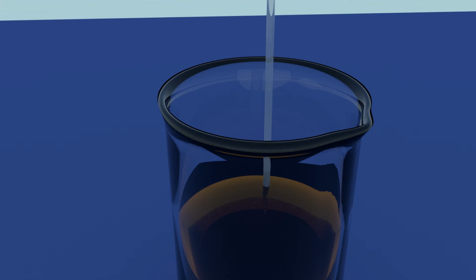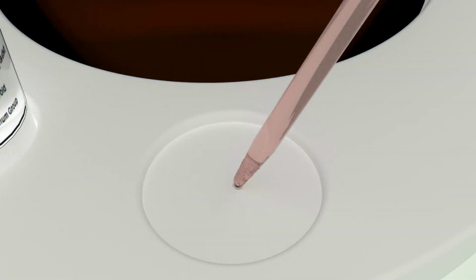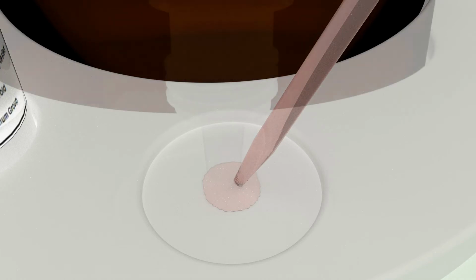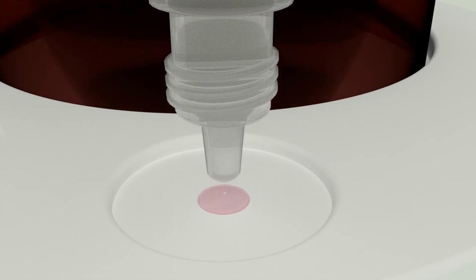To perform this test, you will need to take a sample of your solution. Traditionally, a pipette is used for this purpose. However, since you only need 1 or 2 drops of solution, you can use an eyedropper or even a glass or plastic stirring rod. Place a drop or 2 on a clean paper towel, mirror, or, as seen here, a drop plate. Add 1 or 2 drops of precious metal test liquid to the sample you just took. If the sample changes color to purple, brown, or black, some gold remains dissolved in solution. In that case, add a little more precipitant and give the gold some more time to precipitate out of solution.